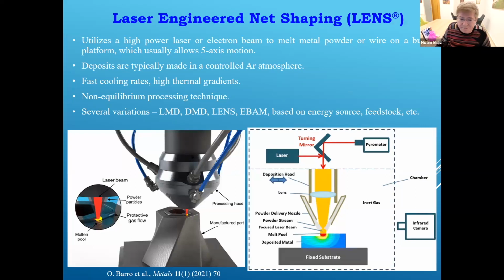On the left-hand side, you have the schematic illustration of the DED process. You have, in this case, a powder feed system with coaxial particle injection setup. I didn't mention, but the DED you can do also with wire. The inset shows the interaction zone with a convergence of the laser beam and powder particles into the molten pool and under inert atmosphere, which is important. And the inert atmosphere in the chamber is more effective than using a shroud, for instance, as we sometimes use in welding.